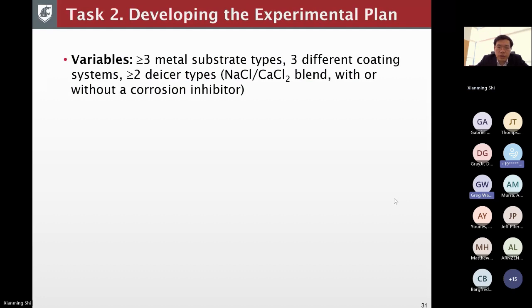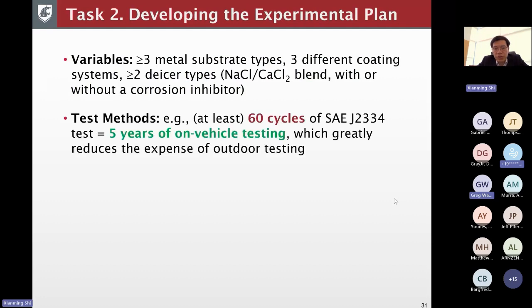As laid out in the scope, we were supposed to investigate at least 3 different metal types and 3 different coating systems, 2 different deicer types. So we end up choosing a blend of sodium chloride and calcium chloride, and actually another one is a magnesium chloride with beet juice.